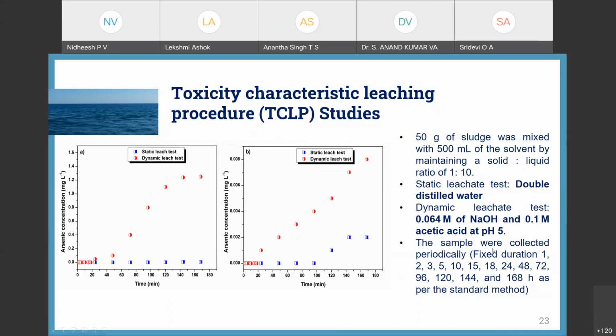Then we need to stir it, for different durations, 1 hour, 2 hours, like this up to 168 hours. We need to take samples at different time intervals. So this is the trend we observed in the static leach test. There is not much leaching from the system, but in the dynamic leach test, that means in corrosive conditions, there is leaching of around 1.2 milligram per liter of arsenic in the water. So if you dispose of the sludge in our environment, it may create some environmental issues. To avoid that, what we did is solidification. Again, we did the leaching test for this concrete.